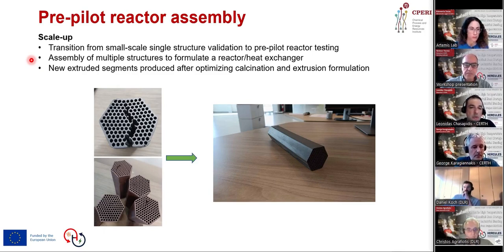So we began by producing new extruded segments of the storage material, which required fine-tuning both the calcination parameters and the formulation for extrusion. This optimization allowed us to achieve mechanically stable and well-shaped pieces, capable of withstanding the repeated redox cycling at the high temperatures. So the final segments had a hexagonal cross-section with cylindrical flow-through channels to maximize contact surface area and enable efficient gas flow through during reduction and the oxidation phases. Next slide, please.